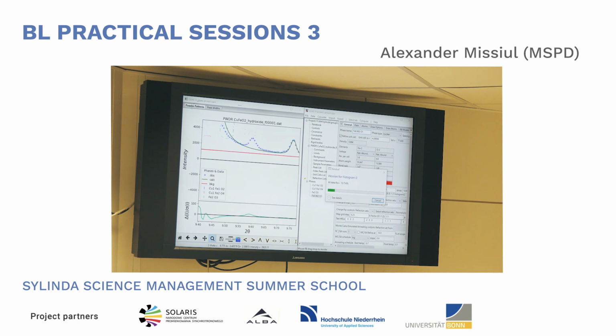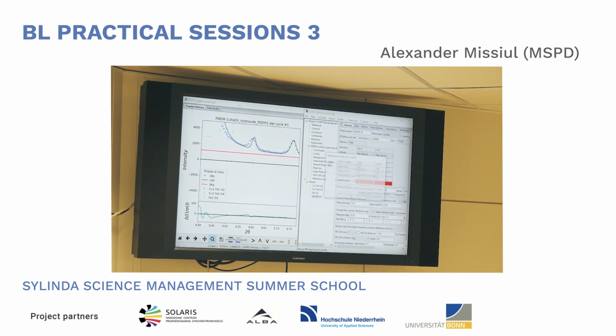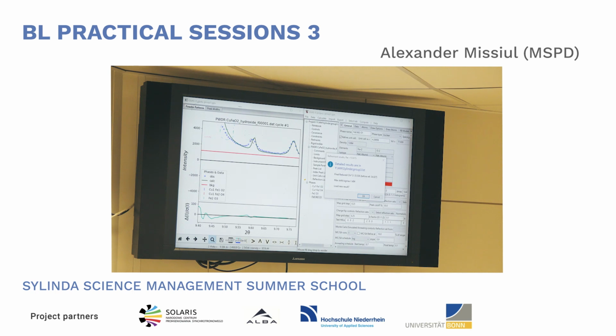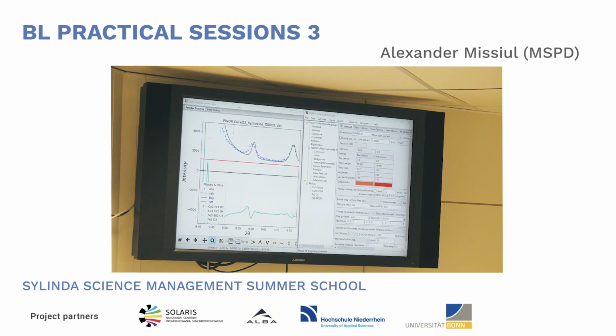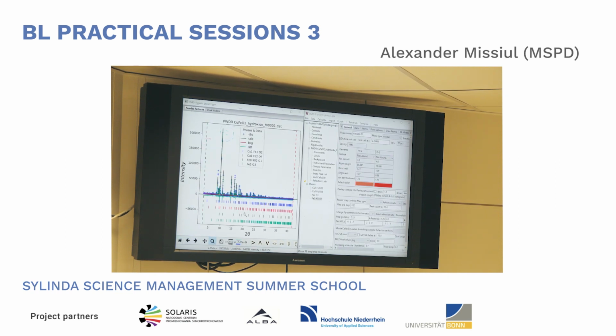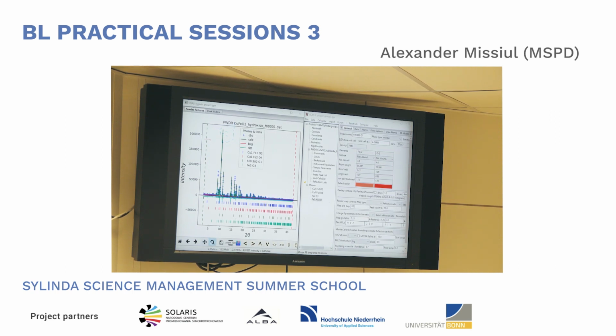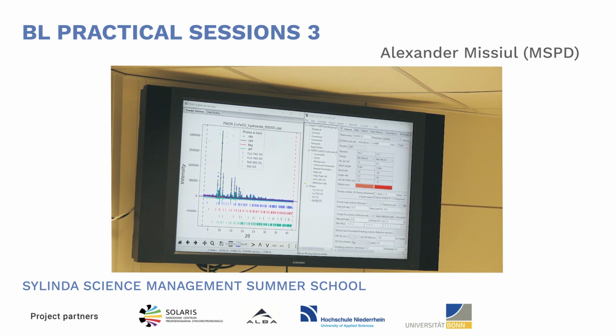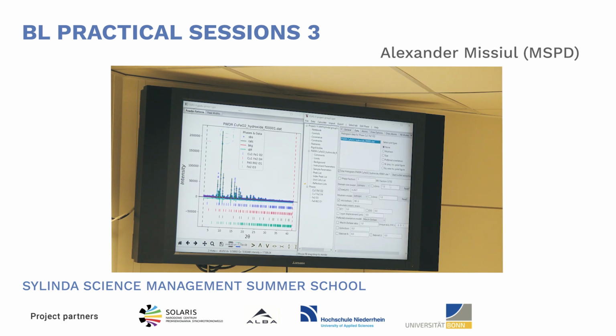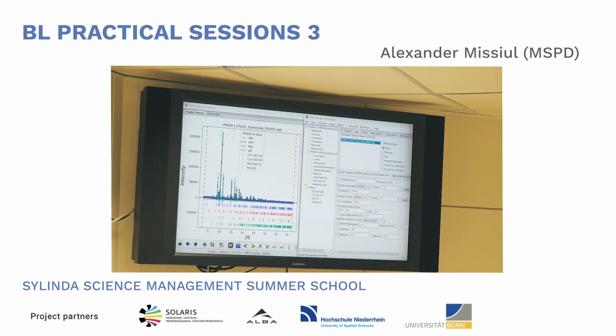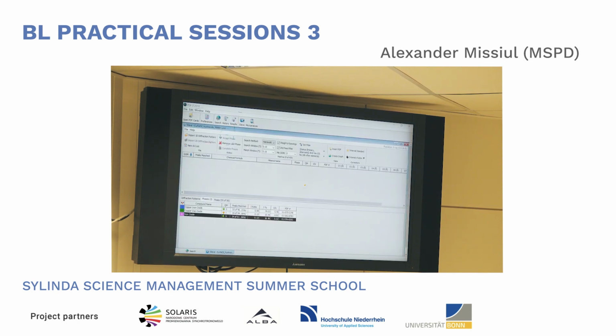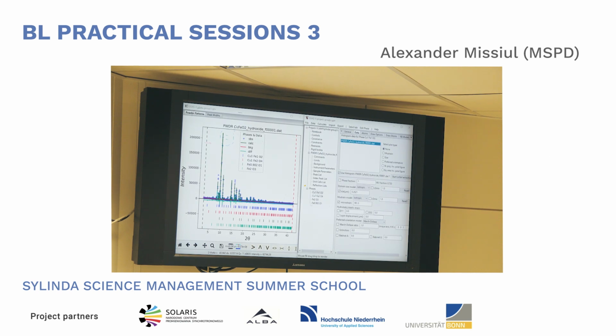Let's just look. So we have the peak here. Again, we immediately see that we might need to change the size or strength and everything, but we will not spend much time. So this is a more or less refined diffraction pattern, not perfect, but for our purpose today, it's good enough. We can say that in our material, in reality, we had 75% of the 1-1 phase. It is a bit different compared to what we had here, right? We had 79, so we have a more precise result.